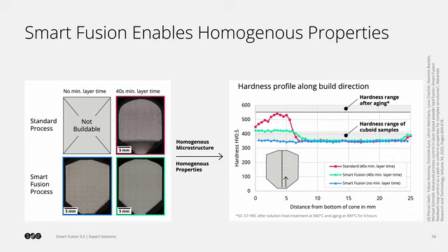With Smart Fusion, the part can be built with or without minimum layer time. In both cases, the etching response appears like the typical MS1. The sample with minimum layer time does show a hardness increase towards the bottom and the top. The reason for this is the same as before: long cooling times and tempering by the next layer, although it is not as pronounced as in the standard sample because Smart Fusion prevents strong heat accumulation. The sample built without waiting times shows a very homogeneous hardness profile regardless of the build height.